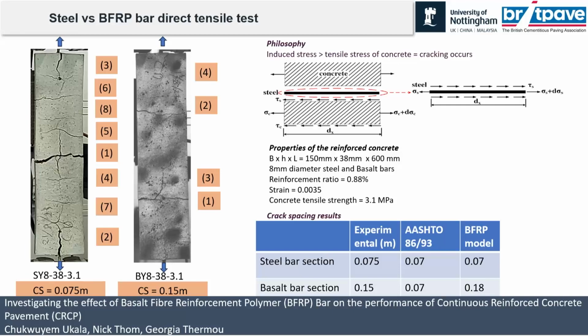And it showed us also in the results, we were able to have about 4 cracks using the basalt section, and also about 8 cracks using the steel. So our crack spacing was much lower for the steel than the basalt, which our modeled result had shown. And when we subjected this to our 2 equations, we discovered that, again, as we have said, this is the basalt bar section, this is the steel, this is that of the basalt model. And we can see that the section fell in between the 2 as we had proposed before.